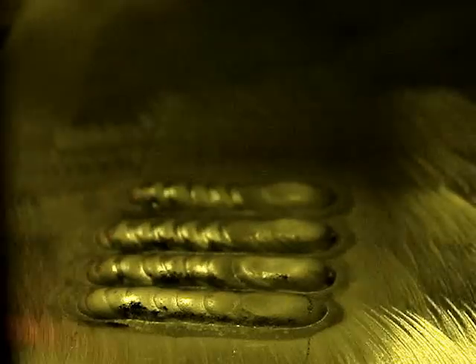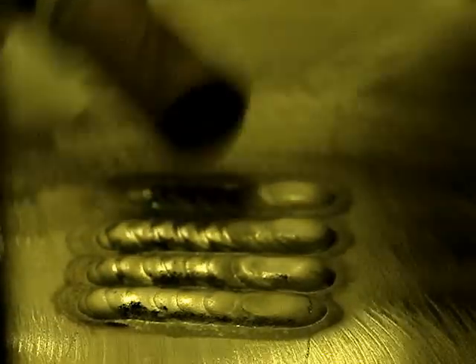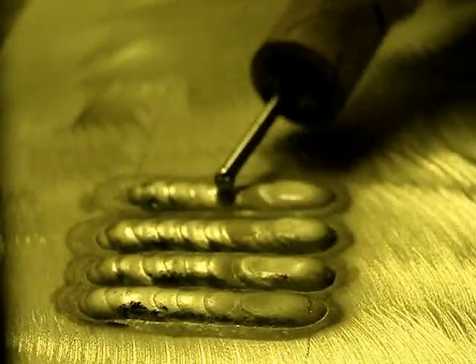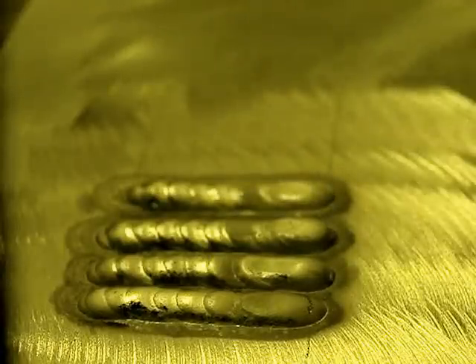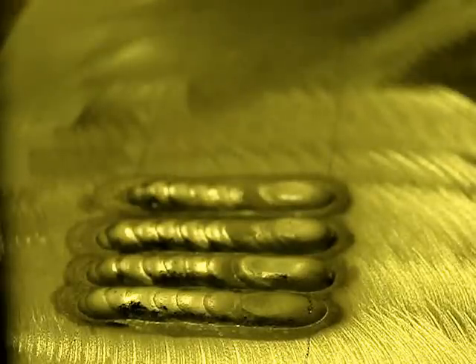Alright, after the 2% lanthanated we went to pure. We're doing this in alphabetical order just to make sure we kept straight. Now, nothing really wrong with pure electrodes other than the fact that I hate them. But a pure electrode at 200 amps balled up like a Tootsie Roll pop on the end. Which if you're welding on 1/4 inch aluminum on a flat surface, that's not a big problem. But trying to weld on an edge or something thin or right next to a bushing you don't want to arc out on, it's a problem to direct the arc when you got a big monkey fist on the end. So pure does not handle the current very well. Old school guys might still like pure. I've never liked it for anything, but that's just me. And I am old school.